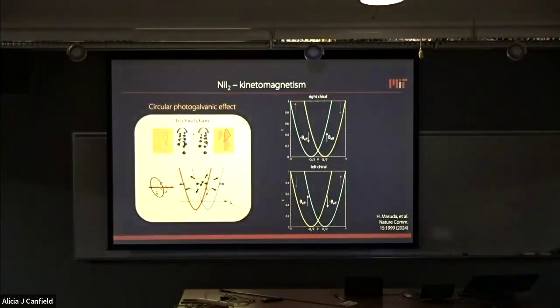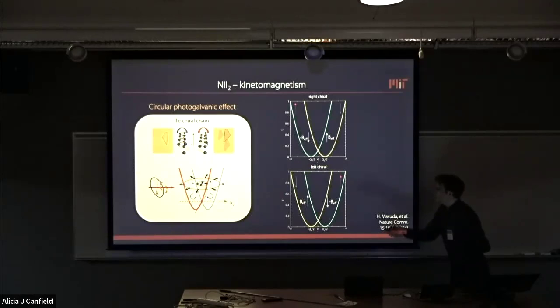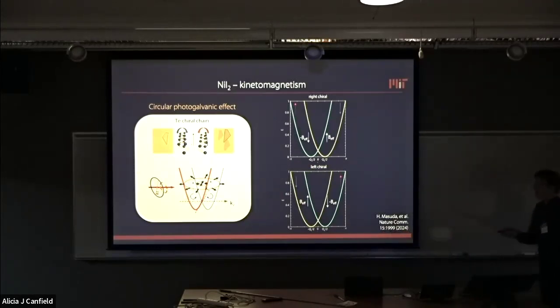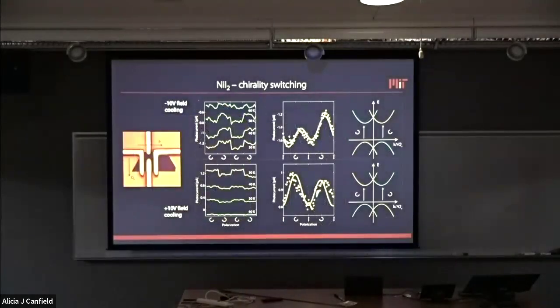So one way to probe this effect is using the circular photogalvanic effect or measurement. So you want to illuminate the sample from the side, so at an angle, such that you transfer some linear momentum, because you want to probe transitions that are on one valley versus the other, and you want to look at the difference in circularly polarized light absorption, and that should, in principle, by symmetry, tell you whether this momentum splitting is taking place. So circularly polarized right light will probe transitions on one side. Circularly polarized left will probe transitions on the other side. And then if you deliver linear momentum as well, you're only probing primarily one side. And so you expect a difference between circularly polarized left and right, just from optical absorption selection rules. So this is exactly what we see in the measurement.